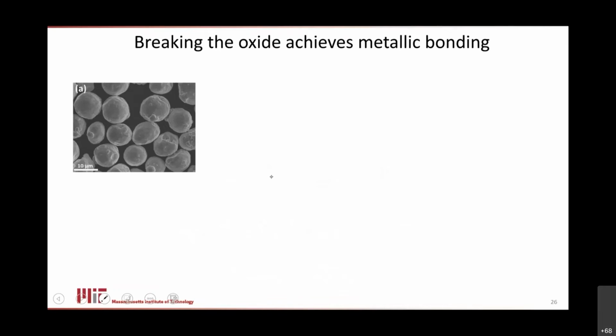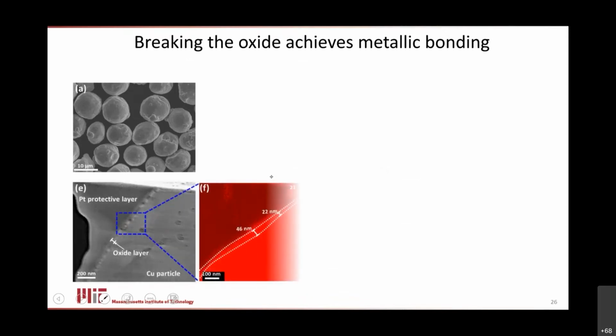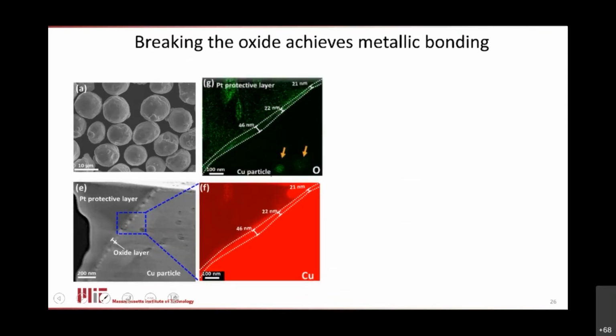So here are atomized powders of copper. We take powders like these, pick the most spherical-looking ones, and shoot them. But you should keep in mind that these powders are manufactured industrially. It's a reasonably clean industrial process, but there is ample scope for these powders to have surface layers on them. There's native oxide, and there are other potential tramp elements around, like carbon. So we are very interested in characterizing those powders.